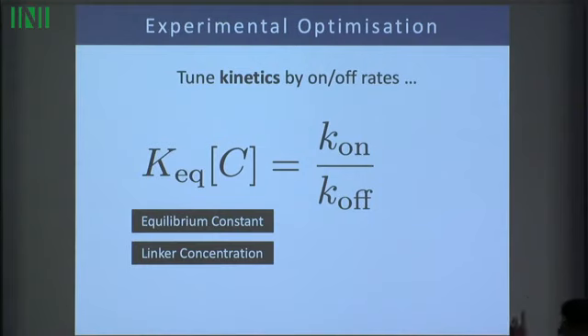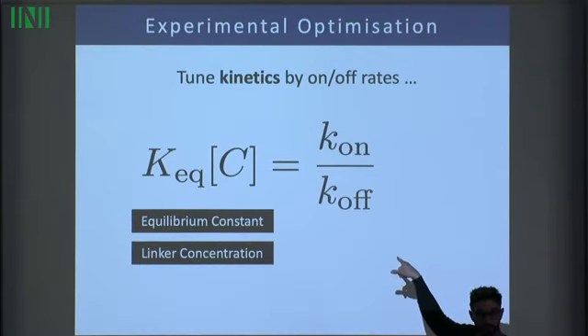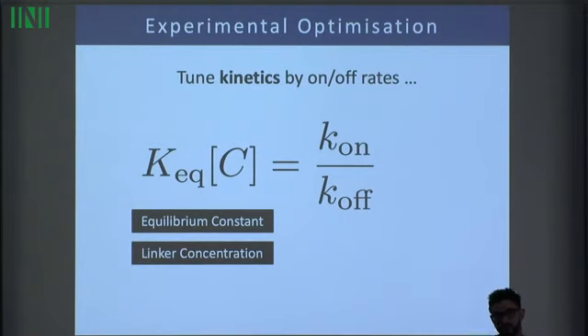So we can get into a weak binding free energy regime, but then we can tune the rate at which we bind and unbind reversible crosslinkers by tuning the K on and K off, the rate constants. It's nice because it's the ratio of those rate constants that determines the KEQ times the concentration. So I can scale K on and K off by any factor I want, large or small, and still be in the same KEQ regime, the weak binding regime, but I can arbitrarily shift the time scale that the exchange happens at.